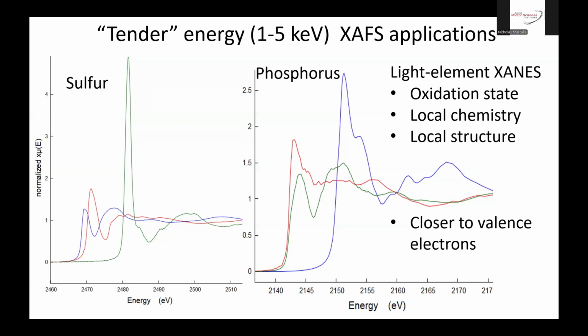So soft X-rays are typically below 1 or 2 keV. Hard X-rays are generally above about 5. It's a debatable definition, but tender energy is somewhere in the 1 to 5 range, in between those two. And that covers elements like phosphorus and sulfur and silicon and calcium. So the lighter element XANES is very sensitive to oxidation state, local chemistry, and local structure, as I said before. For example, sulfur XANES, the different sulfur species are spread out over about a 10 eV range. So it's a nice distribution. So sulfur is one of those really great examples of how things work well.